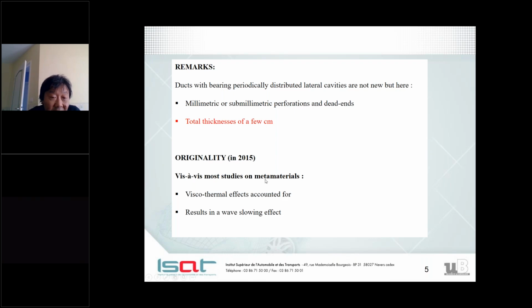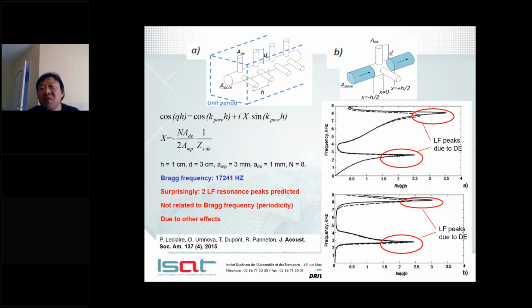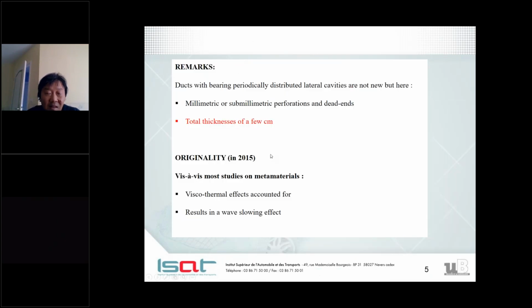So the originality in this study is that the suspected effect is the viscous thermal effects, which are accounted for in this structure at millimetric or submillimetric sizes, and these viscothermal effects result in a wave slowing effect. So if you reduce the sound speed in the structure, you will reduce the resonance frequency. This is a resonator which will be used in the absorber, but you reduce the resonance frequency. So this is the physical effect behind this design.